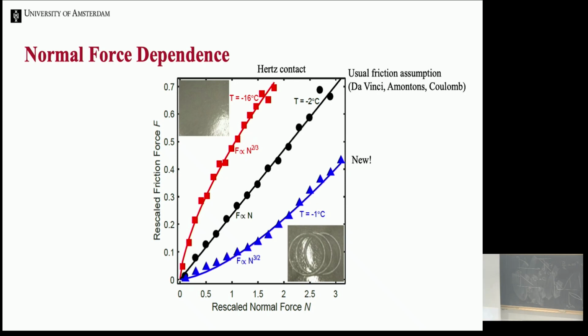Now, what is plotted here is the friction force as a function of the normal force, and that also looks complicated. Yeah, Da Vinci, Amontons, Coulomb, they all say, well, the friction coefficient is the ratio of the friction force to the normal force. And so if that is the case, my friction force against normal force needs to be a straight line. And it is at -2, but if we're too close to 0 degrees, it does something weird. The friction force goes as the normal force to the power 3/2, sorry. And if we're too cold, it also does something weird. It does 2/3. The 2/3, you've all learned in undergraduate physics, is simply the Hertz contact.